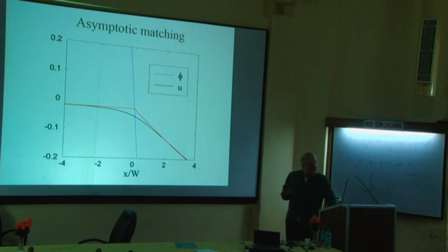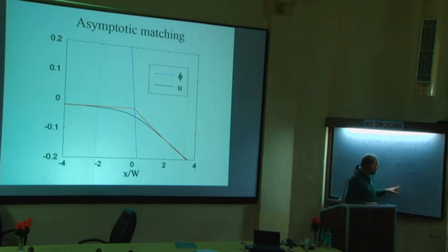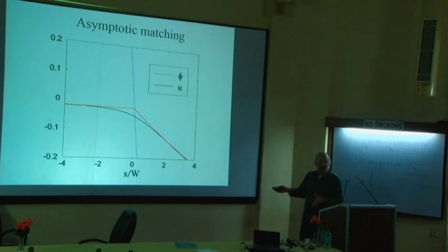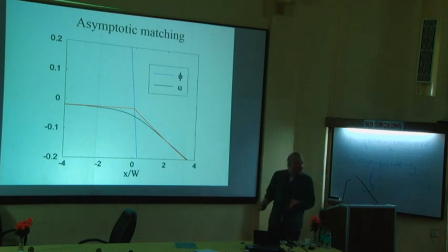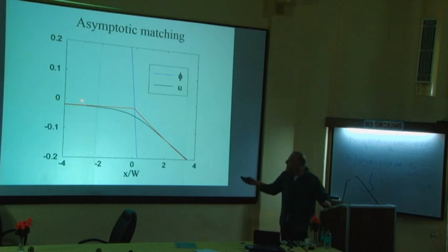And why is this the case? You see, this condition is obtained under the assumption that all the latent heat is released at an infinitely thin interface. Here the latent heat is released wherever the phase field varies. So this heat source term is smeared out over the whole interface. It's diffuse, and therefore this change in slope is also smoothed out and it takes place gradually.